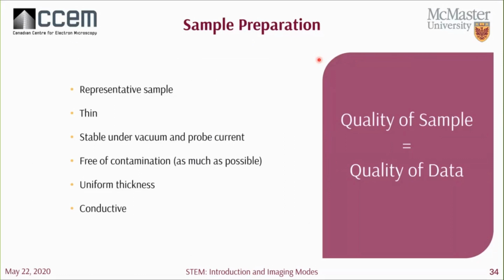Our field of view in the TEM is quite small relative to what you would see in SEM, or definitely up to the optical microscope field of views. So you want to make sure that what you're really looking at is a good representation of your sample. And since we're collecting transmitted electrons, you'll need to make sure that you have a nice thin sample. Generally, the thinner the better. If you have a thick sample, you won't be able to get good signal from it.